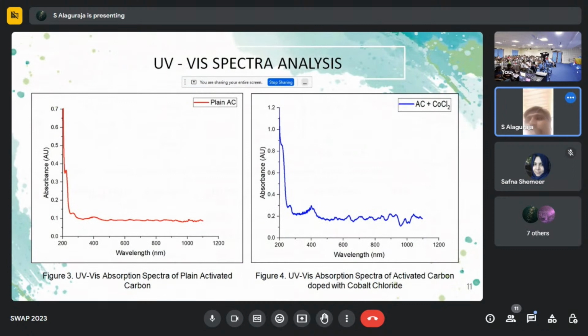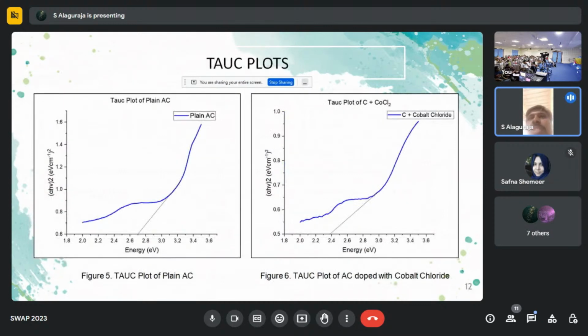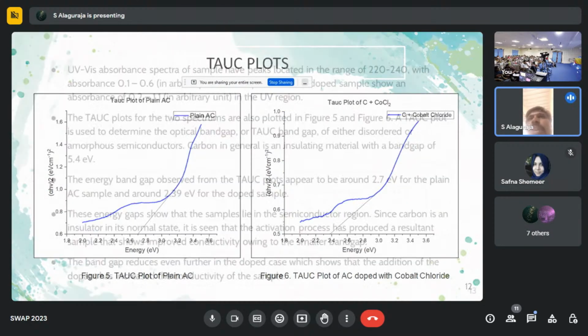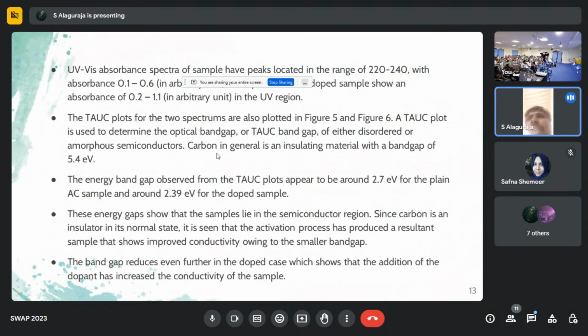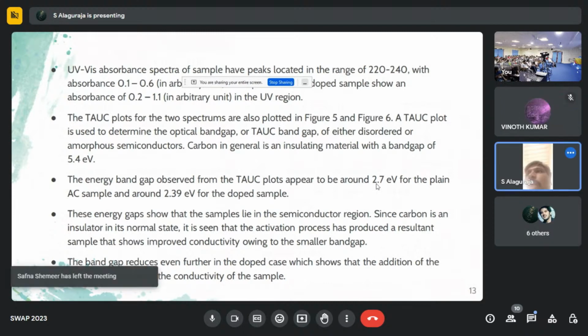From UV spectra, we have plotted wavelength with respect to absorbance. From this data, I can calculate the energy band diagrams with energy and (E alpha) squared. Carbon is generally an insulating material with a band gap of 5.4 electron volts. The energy band gap observed from the Tauc plots appears to be around 2.7 electron volts for the plain activated carbon, and 2.39 electron volts for activated carbon with cobalt chloride doping.